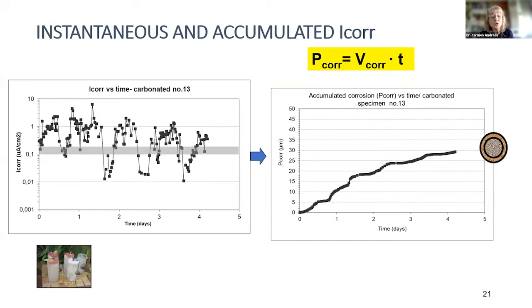Here simply to show that when we are talking about the instantaneous corrosion rate, it changes a lot. But if we integrate in order to have the accumulated corrosion, it follows the typical diagram. I mean, the degree of damage is increasing depending on the seasons and the amount of rain, but it is continuously increasing, the amount of loss of diameter here.